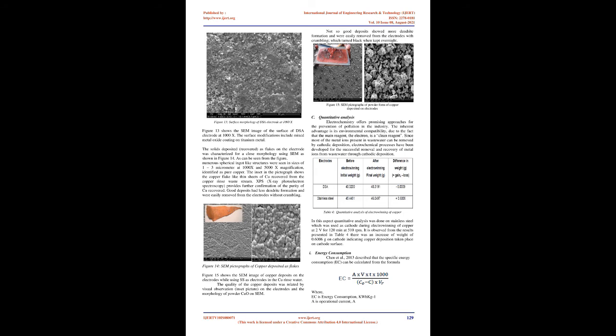Also, the XRD results obtained from this experiment are similar to results obtained in the previous researches of Wahlberg et al., 1996, and Calvo et al., 2009. Figure 10 shows the diffractogram of the deposited copper obtained at 4V for 30 minutes at 510 rpm, which had the copper recovery percentage of 7.93% in monopolar batch study.